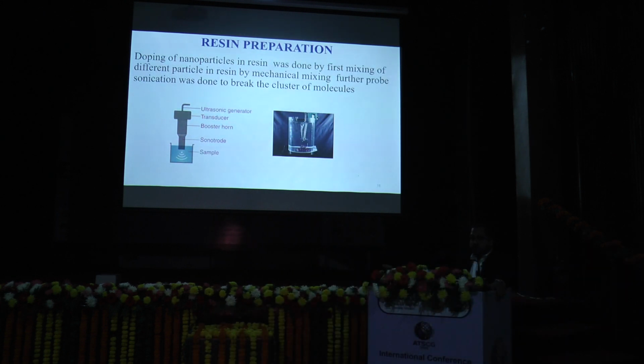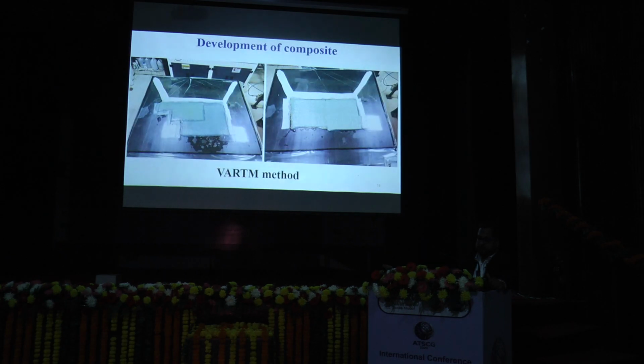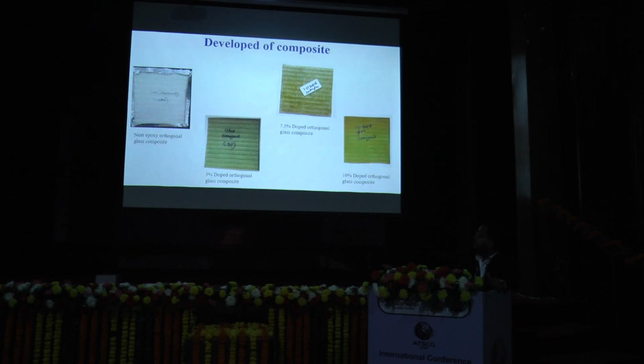Doping of nanoparticles in the resin was done by two different methods. First one is mechanical mixing, and further it is done by the sonication method, ultrasonication method. This is the development of composite by the VARTM method. This is our developed composites. Here we did three doping parameters: 5%, 7.5% and 10%.